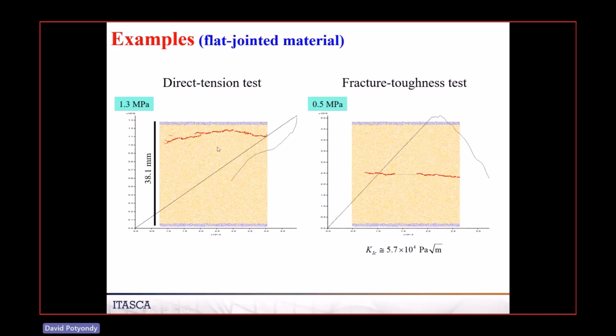And so that thing actually begins, the strain is tensile, tensile, tensile. And then in this region, once this fails, the strain starts relieving itself. And so that's why this thing is kicking back. If we were just measuring strain based on distance between the walls, then this would not be able to go negative. It would not go backwards. It would keep going forwards.